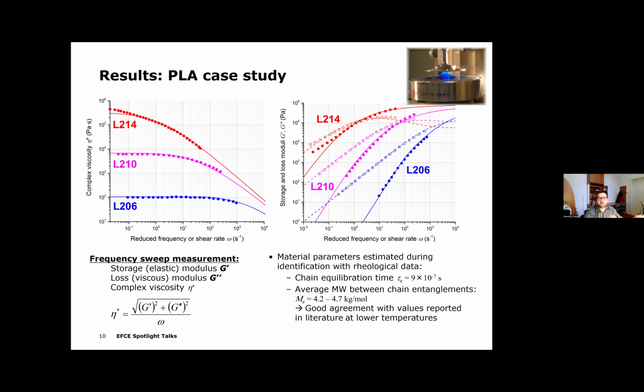On the right-hand side, you can see the decomposition of this complex viscosity into the viscous and elastic parts for 3 different samples, whose names start with the letter L here. The points represent the experimental data from the paper from 1999, and the lines represent the model predictions. With this, we also had to estimate these tau_E and M_E parameters, as I mentioned already. Since the average molecular weight between chain entanglements was quite close to the values we found in literature for PLA, and the agreement between experimental data and model is decent, we considered the modeling framework to be validated by experimental data.